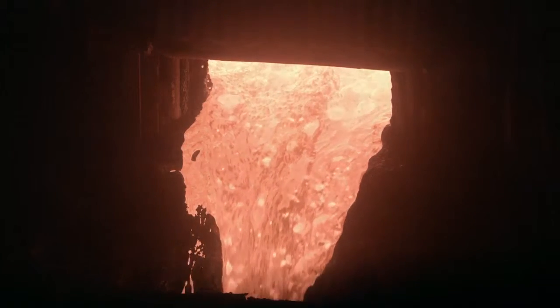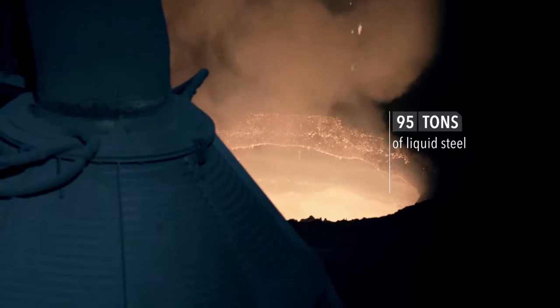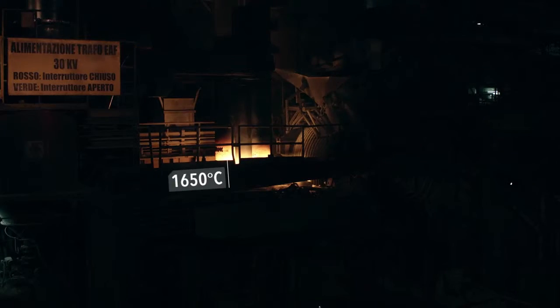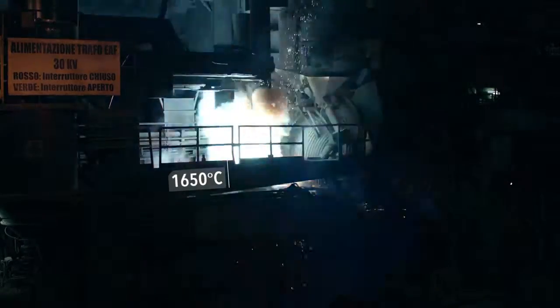When all the scrap has been melted and tapping conditions are reached, around 95 tons of liquid steel at around 1,650 degrees Celsius are poured into the ladle.